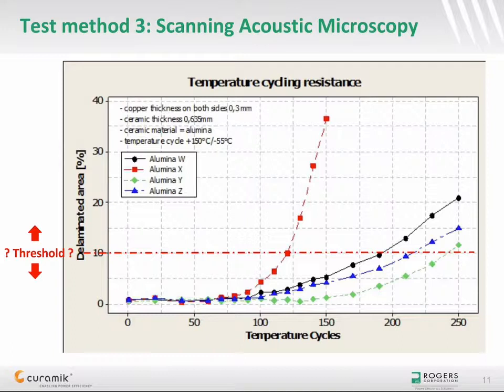At Rogers, we keep on improving the quality and consistency of acoustic images, and we now have suitable equipment and software for image processing. On this chart, the delaminated area for various suppliers of alumina has been plotted as a function of the number of temperature cycles. Once again, it is difficult to give a good definition for end of life, and we may set the threshold at either 10 or 20%. But we can see from this graph that the cracks occur and propagate at different rates depending on the suppliers. This is a very good tool to compare existing materials or suppliers and for the qualification of new materials or suppliers.